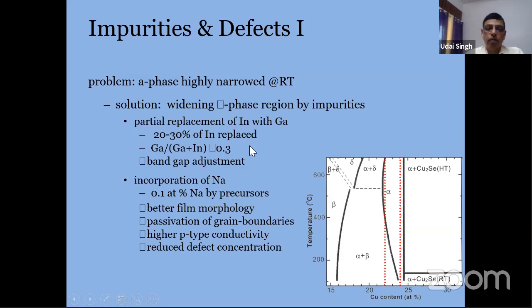certain defects are again introduced. And people have also shown that sodium, at around 0.1 atomic percent, if you put it into this, will also slightly increase this range. It will give a better morphology and passivation of grain boundaries. It will have a higher p-type conductivity and reduce defect concentration. I'm not going into detail on how this works.